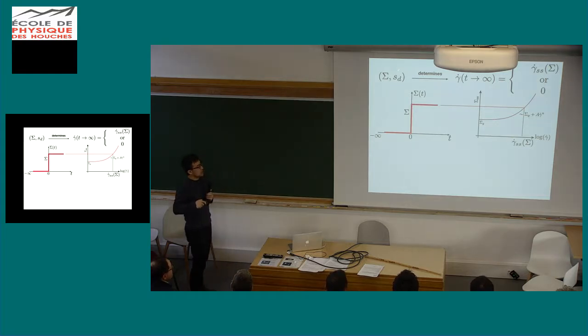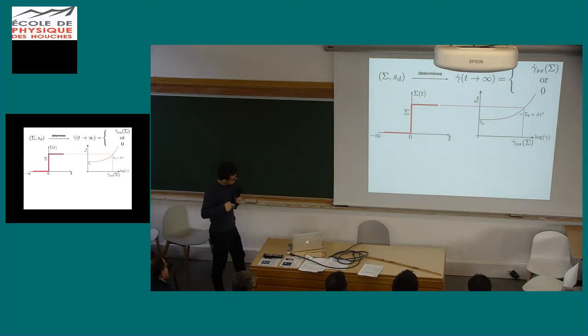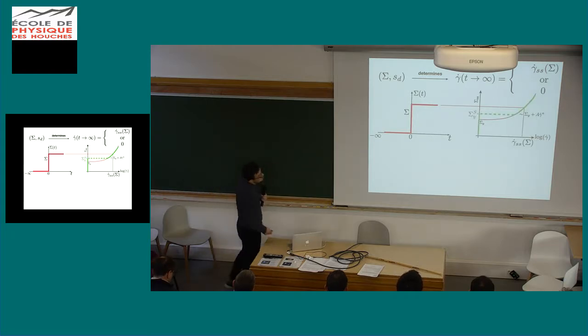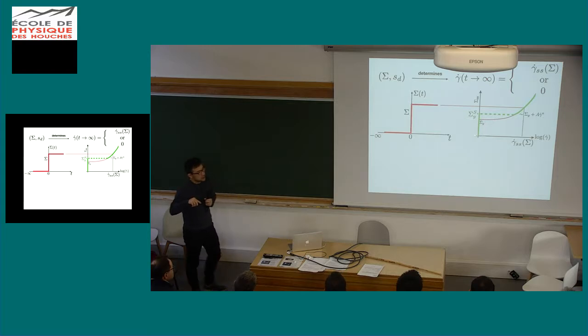In this extreme case, when the spread of the initial Gaussian is really small, you should apply a stress very close to its local yield threshold to make the system flow, and I just told you that the local threshold is very much larger than the dynamic yield stress. So this suggests that there may exist another critical value which is larger than the dynamic yield stress.